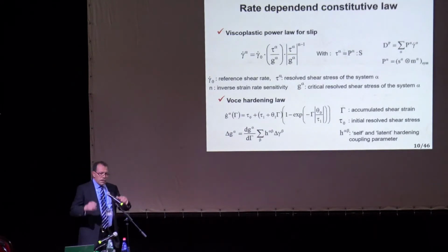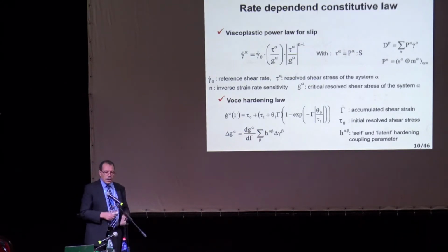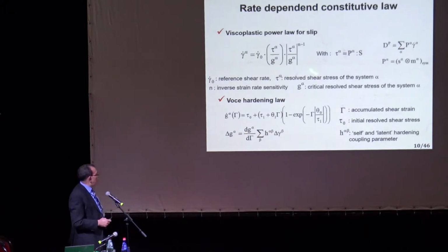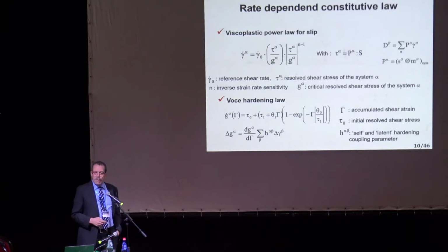Now, with this kinematics for the single crystal behavior, let us look at the constitutive law for shearing or for slip or crystallographic slip. So we use a power law. We could use a different law like an Arrhenius type relationship because these are thermally activated processes, but power law works very well, and from a numerical point of view it's also easy to implement. So this is at the single crystal level. In FCC we have 12 slip systems. So the contribution from each of them would be this gamma dot, which is the rate of shearing.